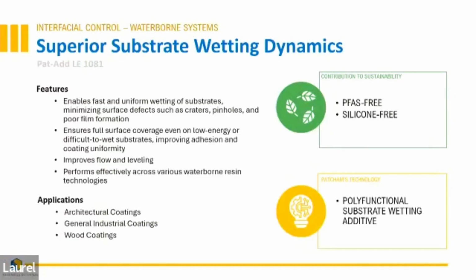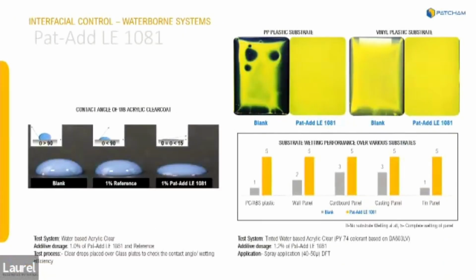And so hopefully you've read all these key points on this item while I spoke. We're going to be talking about a particular technology. If you look at these particular slides, you can see the change in contact angle, the wetting out of that droplet on the substrate. The flatter that drop is, the better, the wetter it is, the lower that contact angle. And then without and with, on a plastic substrate, you can just see the effect.